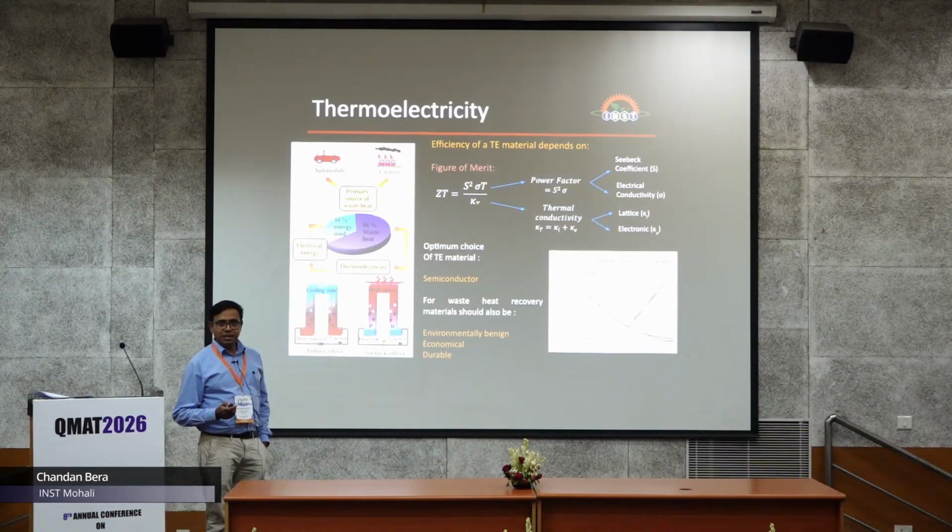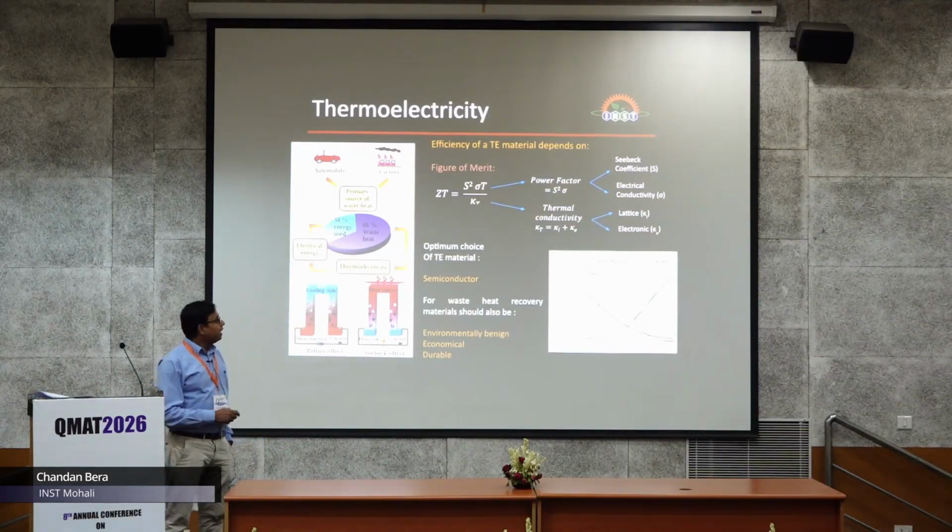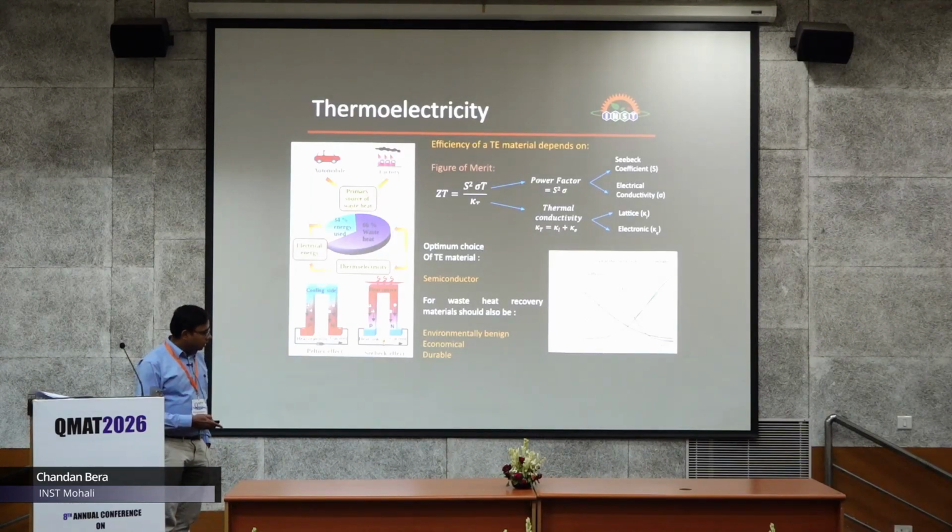Similarly, the thermal conductivity has two contributions: one from the lattice and one from electronic contributions. And the electronic part is also related to the electrical conductivity. So we also need to decouple the electrical conductivity and thermal conductivity to improve the thermoelectric figure of merit.